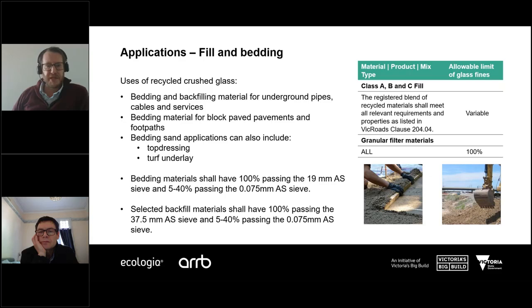So typically our bedding materials would have 100% material passing 19mm sieve size, and still be a graded product with 5 to 40% allowable passing the 0.075mm sieve size, so the 75 micron sieve. And again, there's some fairly similar rules around backfill materials. This material is allowed to be a bit coarser than bedding materials, but again, it's fairly similar rules.